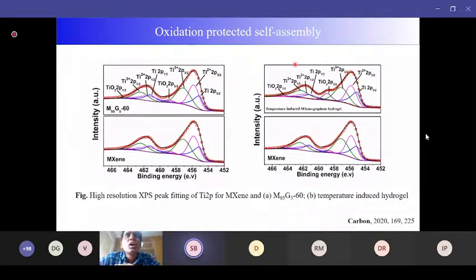And we changed the oxidation state. This is one of the keys of that publication: whenever people do some assembly of graphene with the MXene or some processing, they used to use some hydrothermal method, some temperature-involved method. But these MXene sheets are very susceptible to oxidation. So if someone uses some thermal treatment even at just 90 degrees Celsius, you can see that the other peaks like Ti2+, 3+, and Ti 2p, these are of MXene, but here there is a peak